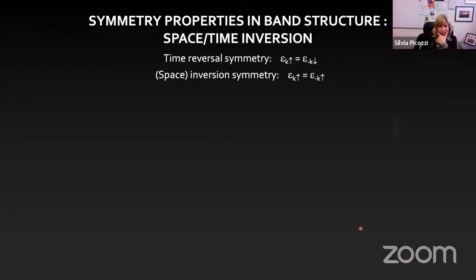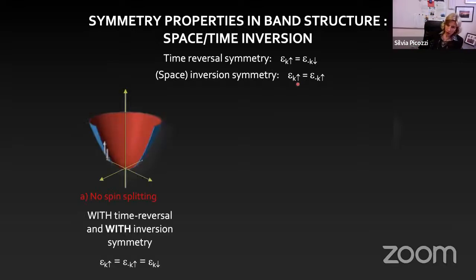So, okay, if I start very generally from the constraints that are imposed by symmetry on the band structure, then one can say that if time reversal symmetry is kept in my system, then the eigenvalues for positive momentum k with spin up must be the same as the eigenvalues at minus k with spin down. And if I have space inversion symmetry, a centrosymmetric system, then the eigenvalues at k and minus k for the same spin channel need to be the same. So if my system has both time reversal and inversion symmetry, then there cannot be any spin splitting. So all my bands are doubly degenerate.